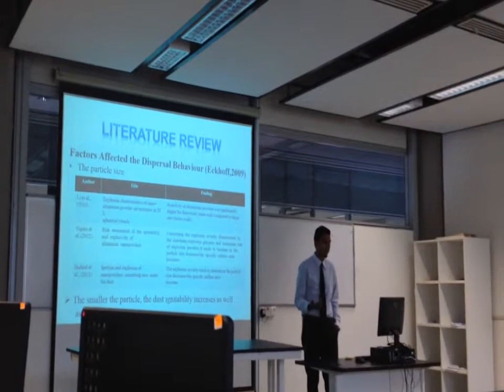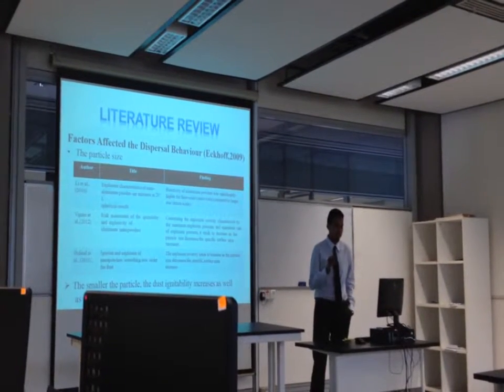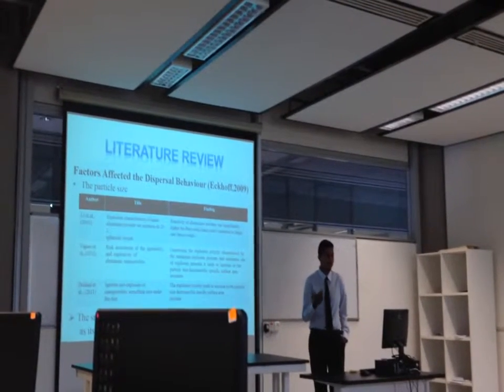Next is Vignes et al., with research on risk assessment of ignitability and explosibility of aluminium nanoparticles. They found that explosion safety characteristics — maximum explosion pressure and maximum rate of explosion pressure rise — tend to increase as particle size decreases or specific surface area increases. Similarly, Dufaud et al. found that explosion stability tends to increase as particle size decreases. We can conclude: the smaller the particle, the higher the ignitability and explosibility.